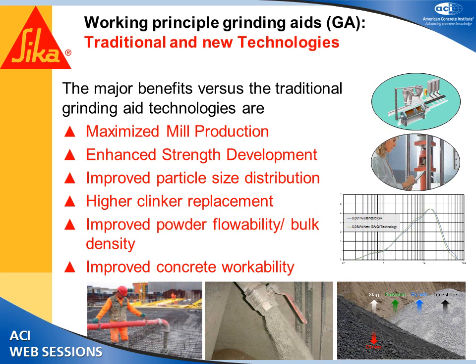Producers generally don't increase the clinker replacement because when they do that, they'll have to grind it more to get the same kind of activation. But using PCEs, because it improves production, you can go for higher replacement levels. Improved powder flowability and bulk density, and sometimes in tailor-made admixtures you can also have improved concrete workability.